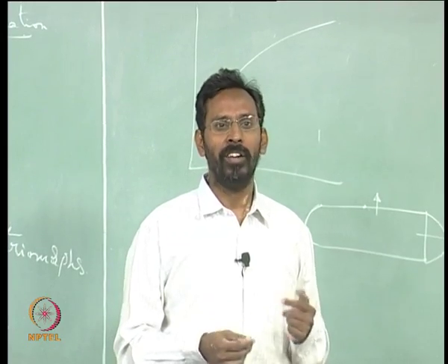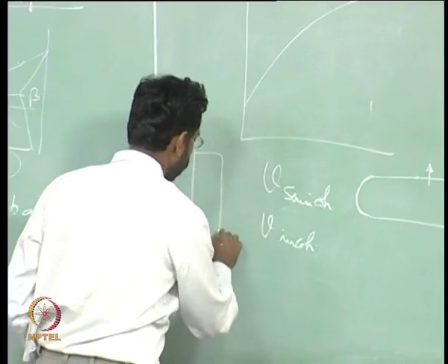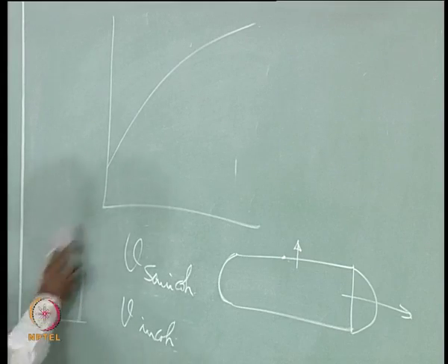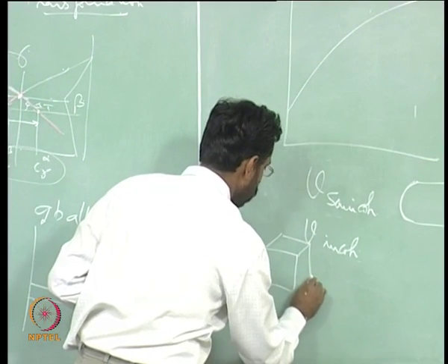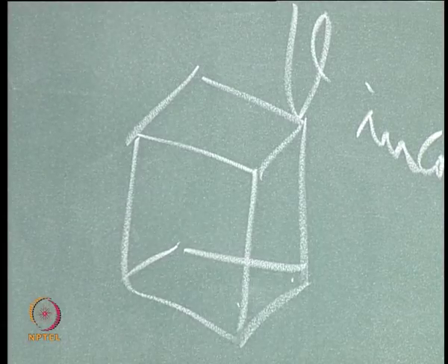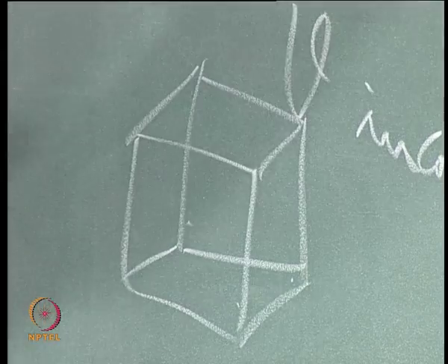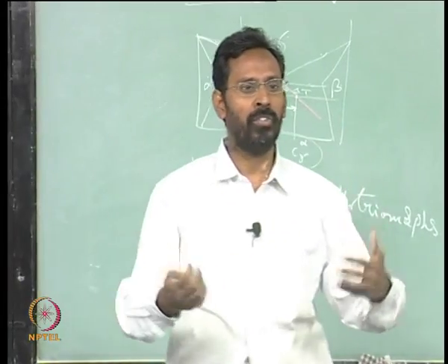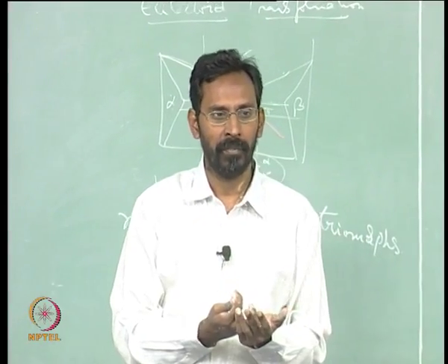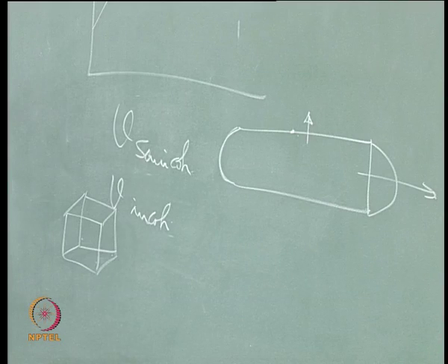That is because whenever you look at any precipitate, for example a nucleus has formed something like this, or maybe initially you imagine it is like a cube, because silicon, let us say, is cubic in nature, diamond cubic. So some nucleus has formed, and this nucleus has to now grow. The growth depends on the rate of atoms joining from the liquid to that silicon, and not only that, it also depends on which plane needs fewer atoms to grow.